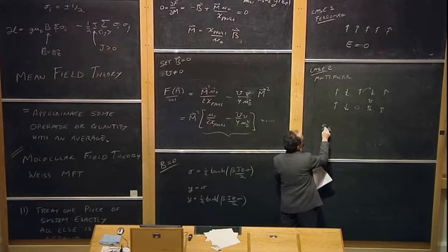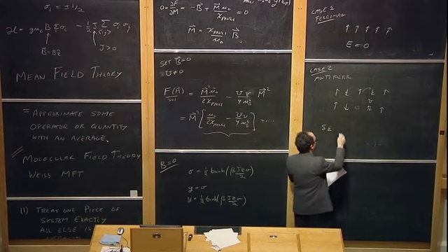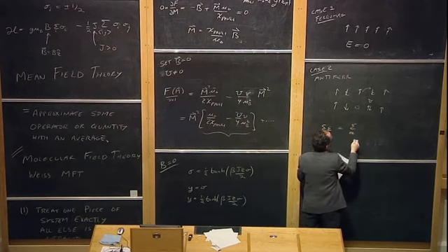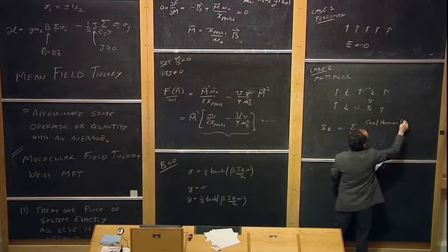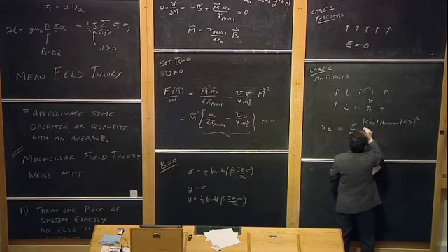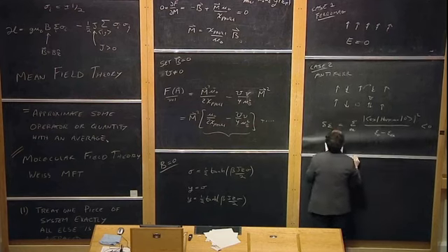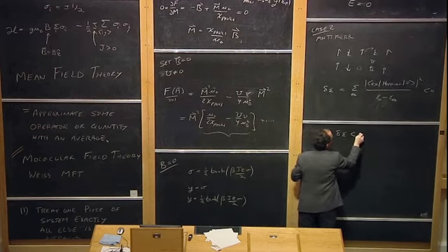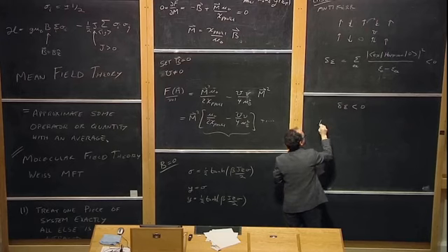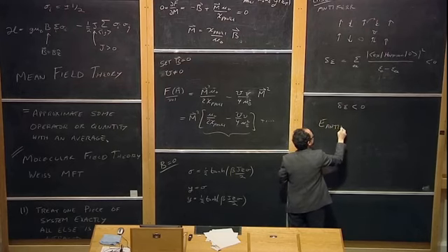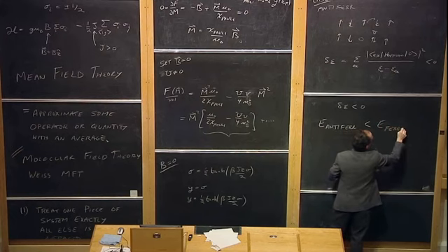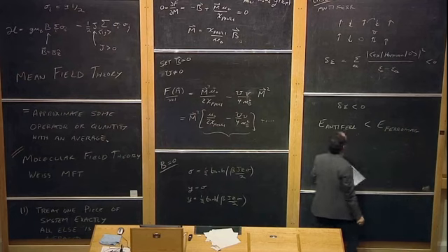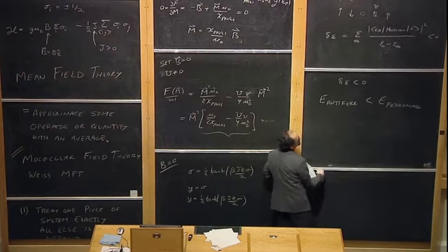And so in second-order perturbation theory, due to this sort of hopping process, you get a shift in the energy, which is the sum over all possible excitations of the excitation, hopping Hamiltonian, ground state, squared, over energy 0 minus energy of the excited state. And this is less than 0. So in fact, the change in energy is less than 0. So the energy of the antiferromagnet is less than the energy of a ferromagnet when you have 1 electron per site in this Mott insulator limit.